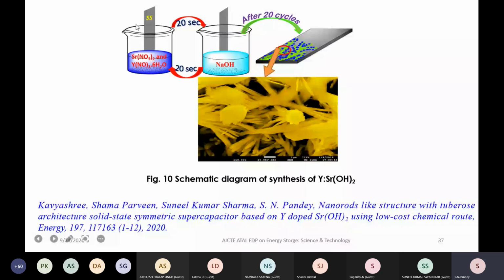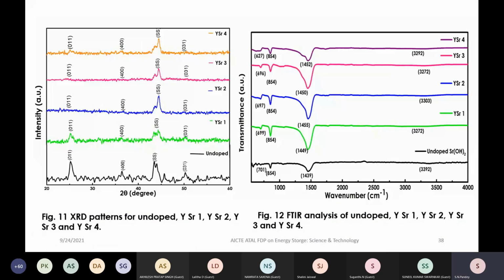The same method has been used here, with strontium nitrate and Y(NO3)3.6H2O taken because we are making the doping. A fixed amount we have to take and mix with strontium nitrate so that one can get proper doping. Then for 20 cycles, we again optimized the number of cycles. After 20 cycles the thin film has been formed, and one can see the structure here.